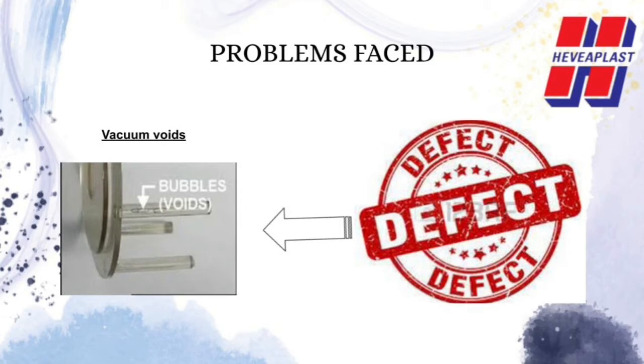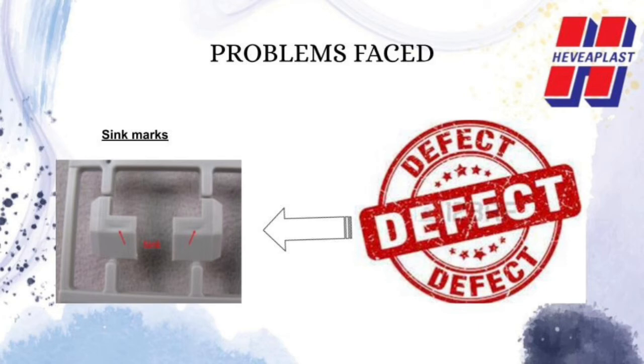The first defect that can occur is vacuum voids. Vacuum voids are pockets of air trapped within or close to the surface of an injection molded prototype. Vacuum voids are often caused by uneven solidification between the surface and the inner sections of the prototype. This can be worse when the holding pressure is insufficient to condense the molten plastic in the mold and thereby force out air that would otherwise get trapped. Voids can also develop from a part that is cast from a mold with two halves that are not correctly aligned.